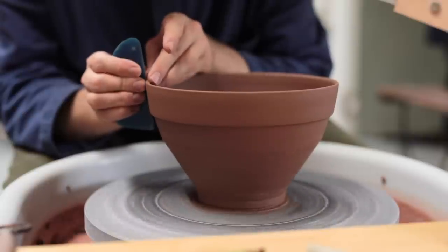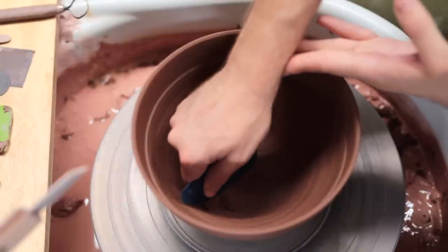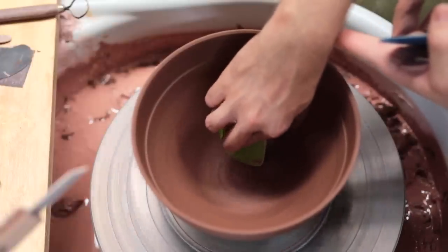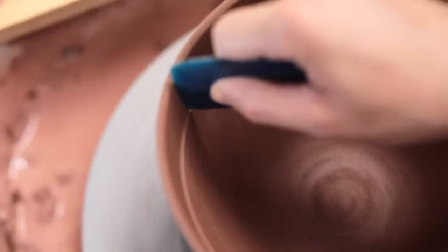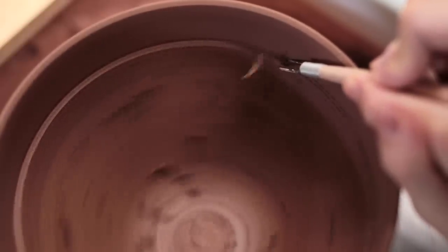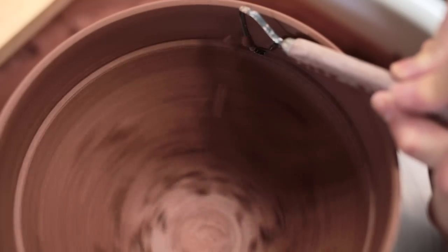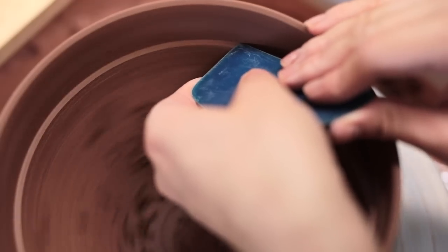I also pushed the rim of the bowl out against the plastic kidney, but at this point, to really refine it, I think I need to trim the rim from the top down. But first, I spent some time cleaning up the interior form, scraping away the more prominent throwing rings and defining this interior edge, which was roughly formed at the throwing stage. Now the clay is leather-hard, I'll have an easier time getting it to the exact shape and sharpness I want. In order to trim this detail, I had to make sure there was enough material left in the pot at the thrown stage. If I threw it really thin, I simply wouldn't be able to refine the shape like this without risking the destruction of the vessel. So when producing pots with particular details like this, I purposefully leave them on the thicker side, to then be able to trim them back.